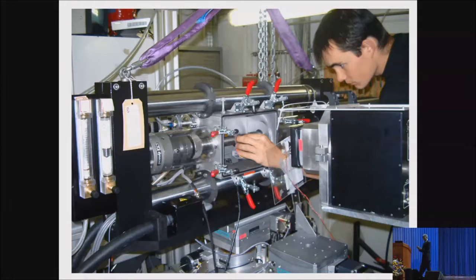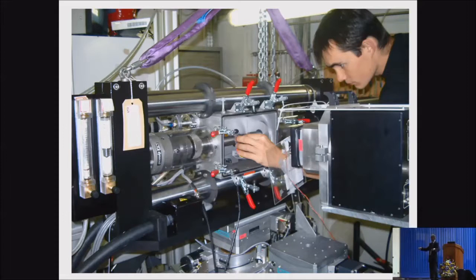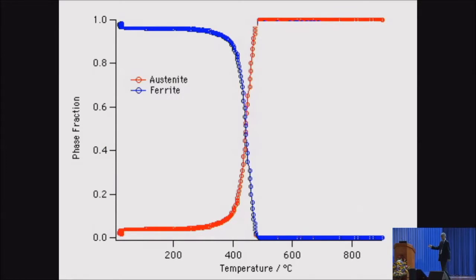And we did a more complicated Satoh test, where we take a tensile specimen, we constrain it at a high temperature, allow it to cool, and monitor the strain. This is a synchrotron, where you have high energy X-rays going through your tensile specimen while you do the Satoh test. So that means we can follow the amount of austenite and ferrite that forms as a function of temperature during the tensile test. And here you can follow the phase fractions as transformation happens. The blue curve represents the ferrite, and the red curve represents the austenite, and this is the commercial electrode.